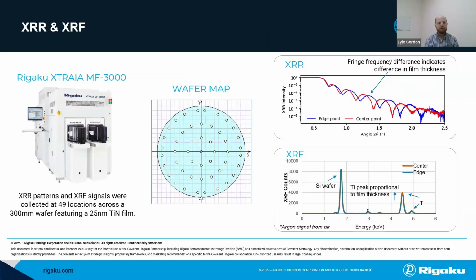So we'll show an application using a Rigaku XTRAIA instrument. This is a semiconductor tool that can map full 200 and 300 millimeter wafers. In this case, we collected 49 locations across the wafer using both the X-ray reflectivity as well as the X-ray fluorescence. And we can generate a map of that thickness. And this is nominally a 25 nanometer thick titanium nitride film. So you can see in the top right, showing the edge in blue and the center in red, that there's a really obvious difference in the film thickness from that fringe frequency.